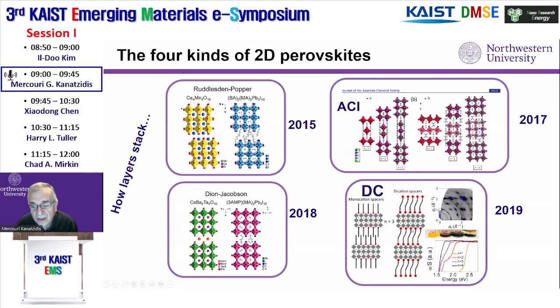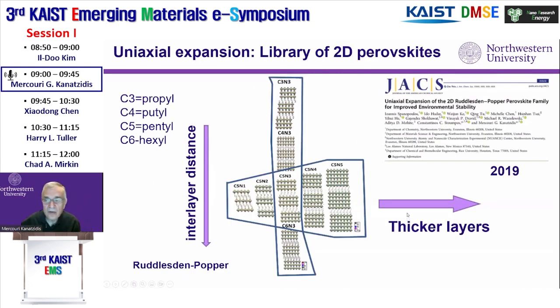And then we also have this one that has dications across. So now you expand the chemistry horizons really to a big degree, because now you can start experimenting with everything here. So you can have the same spacer, and you can start making the layers thicker in one study, or you can have the same thickness and change the spacer. And we did extensive studies on this and stabilities, and we found that these are much more stable than the 3D perovskites.